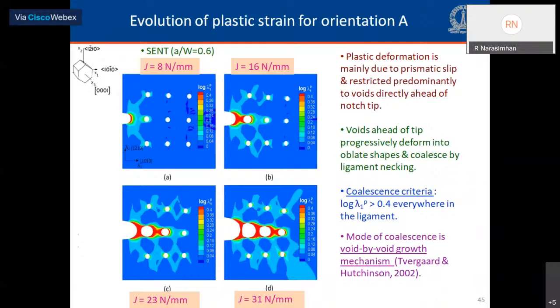The evolution of slip and twinning is quite similar in both the specimen geometries. So I'll just show very representative results. These are for the single-edge notch tension specimen, and you see a sequence of plastic strain contours as the energy release rate J increases. In this case, as we saw from the unit cell simulation, prismatic slip is basically active.